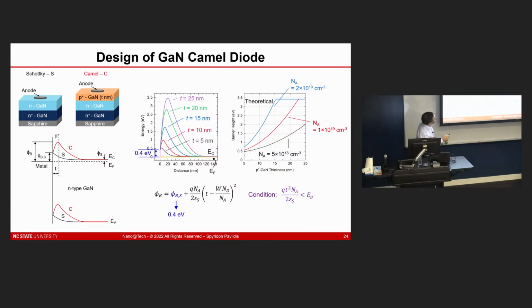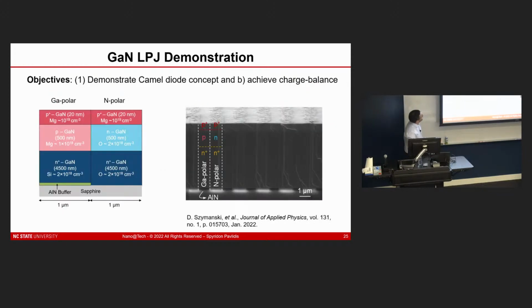And we did various TCAD simulations to look at how this relationship exists between thickness and, as we go to this chart, between thickness and doping. So there's two design knobs there that you can use. But effectively, this gives you a way to add to your reference Schottky barrier diode, your Schottky barrier for your barrier height for your Schottky diode, via engineering this P layer. So that's what we aim to do here, and we designed this structure where we introduce this thin P-GaN layer with very high doping on top of now the lateral polar junction with the gallium polar and the nitrogen polar regions side by side.